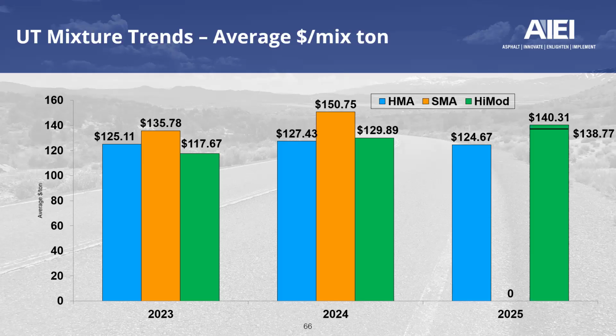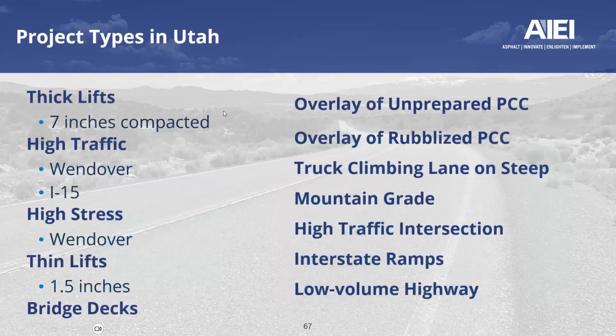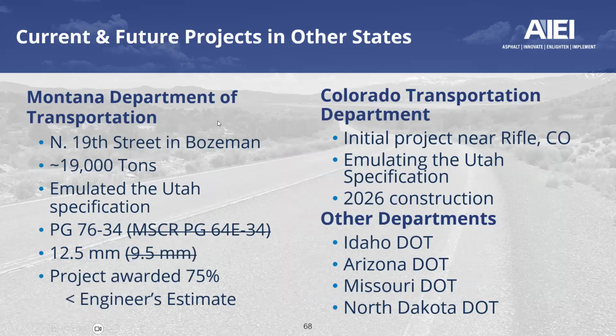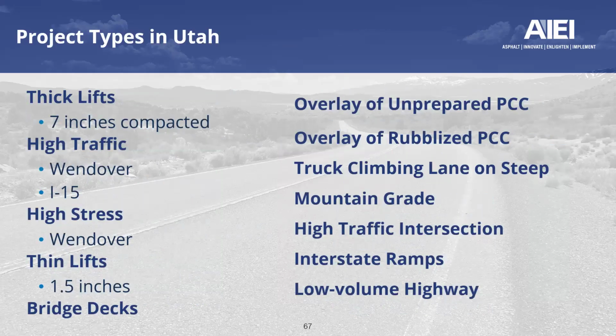Where has it been used? Well, kind of everywhere in Utah. It has become the dominant mix. I mentioned over 500,000 tons were contracted in 2024. Last year, they placed a little over 600,000 tons, and we're seeing it in thick lifts as thick as 7 inches compacted. We're seeing it in very high traffic areas. Wendover is the shining example of that at the truck weigh station.